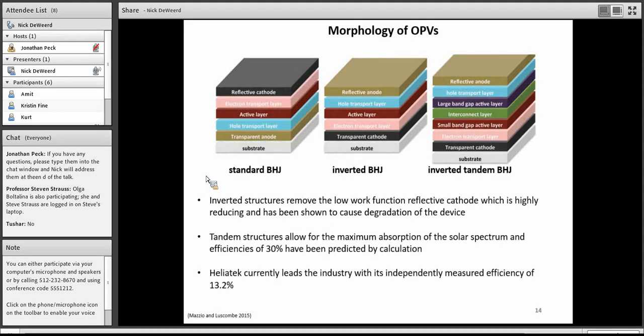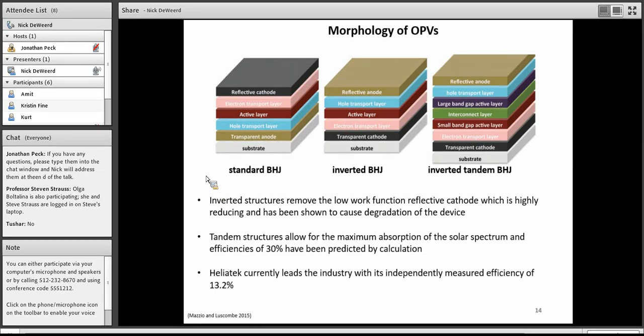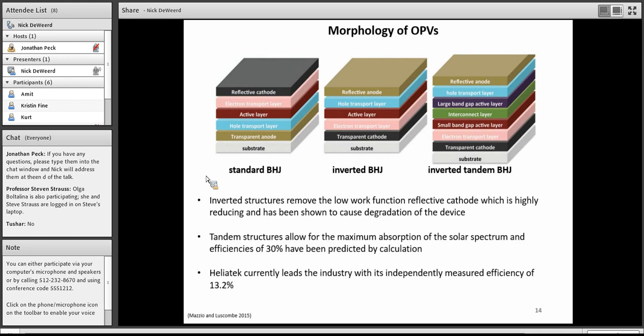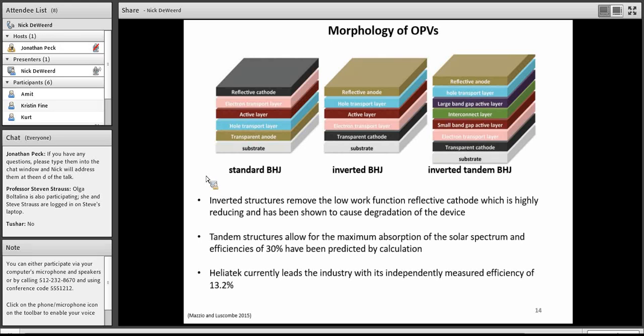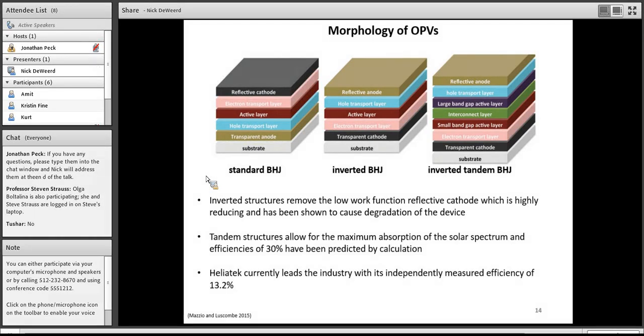If we stick with the bulk heterojunction, there's a few different versions of that that have been developed over time. We have the standard bulk heterojunction. That's going to look a lot like a traditional photovoltaic. Then you have the inverted bulk heterojunction. That's actually where the anode and cathode have been switched so that you've flipped the device, hence the name inverted. That's predominantly because having a low work function cathode, which ends up being very reducing, has been shown to cause several different degradation pathways that are present in the device. This can be due to water or oxygen or just the acidity of a lot of these common low work function cathodes. So by flipping this, you can avoid that because you can use a higher work function cathode at that point. You can use something like molybdenum oxide or zinc oxide and replace the more corrosive cathode materials that have been used traditionally in standard bulk heterojunctions.